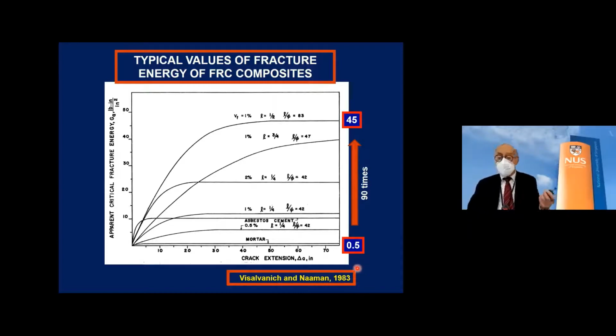And I show you this result, which shows here what we call the apparent critical fracture energy. For the mortar, 0.5, whatever the number, don't worry about the number. For 1% of this particular steel fiber, 45. So in a way, by putting 1% steel fibers, I'm observing 90 times the energy, not 90%, 90 times the energy absorption capacity, or if you want, 90 times the surface energy of the material. Okay. Today, we can do 1,000 times. Okay, and we did it with Sifcon and some other material.